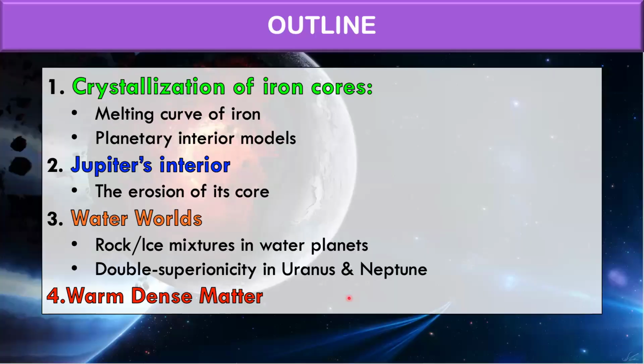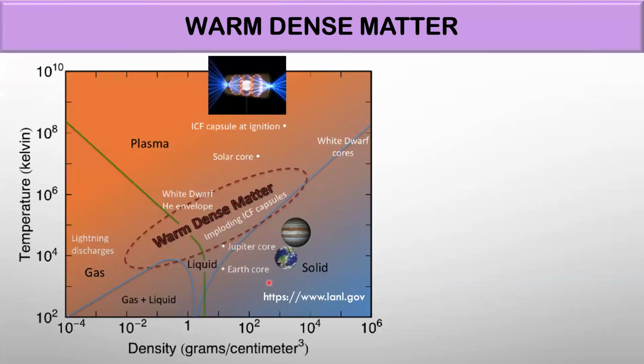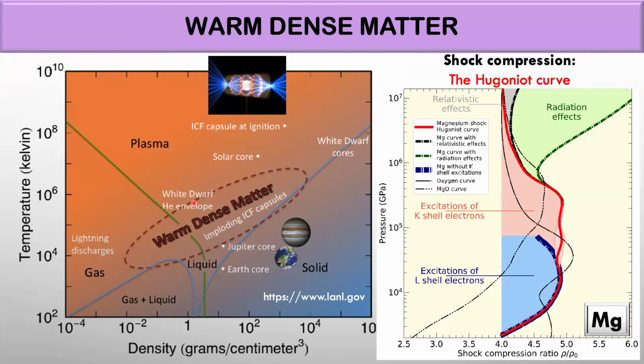Okay, and since we do have a little bit of time, I will tell you a little bit about this warm dense matter that I told you about at the beginning, which again is this phase of matter that appears when you have really, really high densities and really, really high temperatures at the same time. So it encompasses the imploding capsules in the Livermore experiments. You can see that there are densities that can be higher than Jupiter's core, but are particularly relevant for white dwarf envelopes. What happens with matter at these extremes is generally characterized by shocks that I told you a little bit about at the beginning.